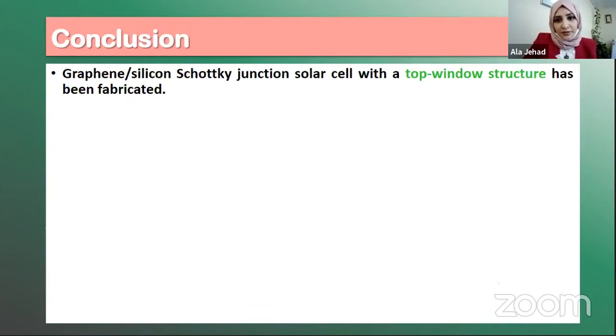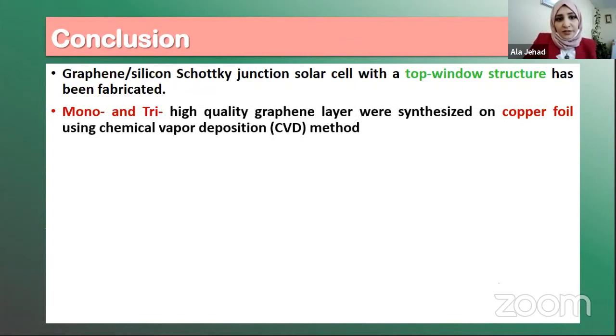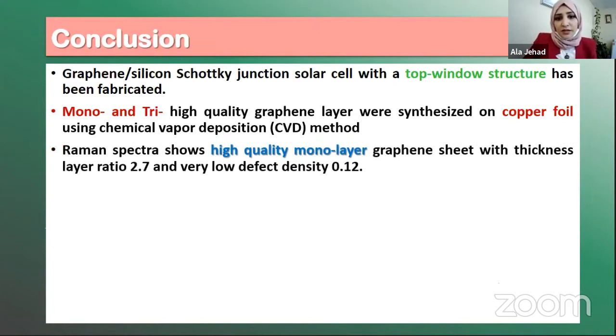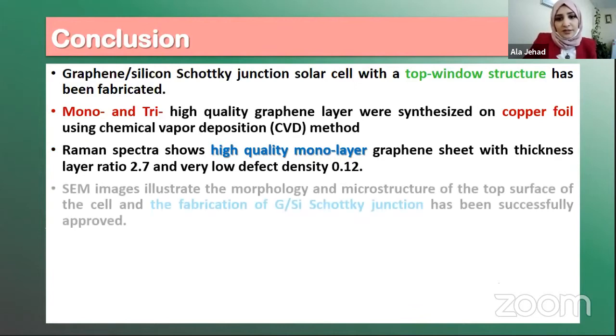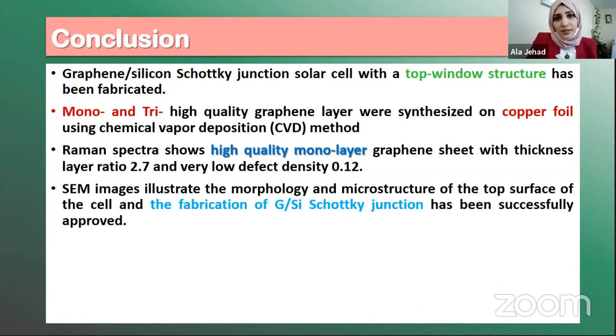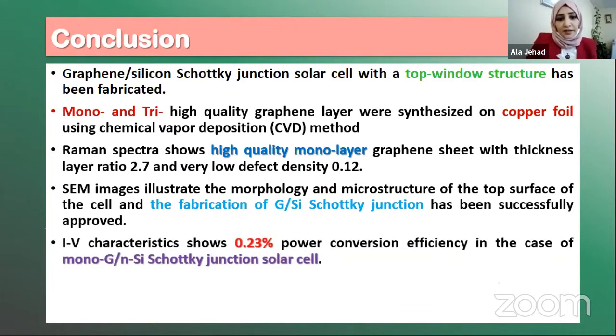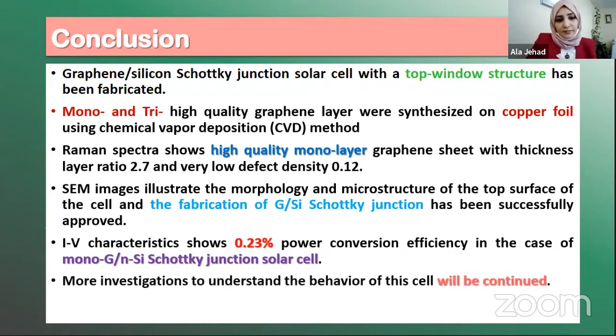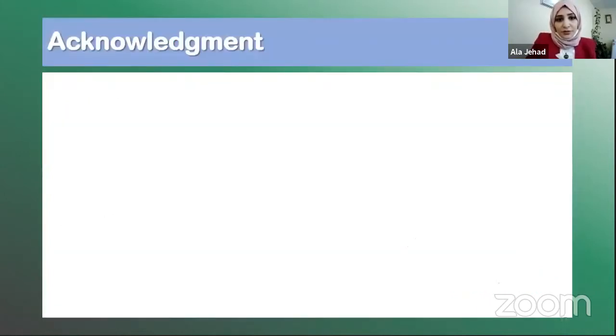Conclusion: a graphene silicon Schottky solar cell with top window structure has been fabricated. Mono and tri-layer graphene has been synthesized with the assistance of copper foil. Raman shows high quality monolayer graphene with 2.7 thickness layer ratio. SEM illustrates the morphology and the microstructure of the cell. And IV shows 0.23 power conversion efficiency in the case of N-type silicon. And more investigation to understand the behavior of the cell will be continued.